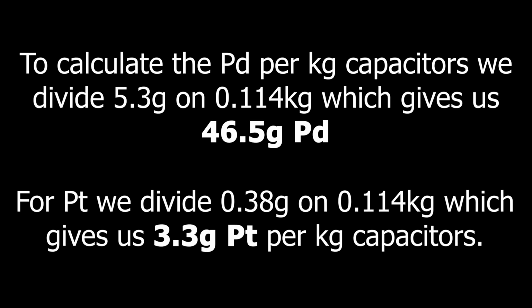To calculate the palladium per kilogram capacitors, we divide 5.3 grams by 0.114 kilograms, which gives us 46.5 grams palladium. For platinum, we divide 0.38 grams by 0.114 kilograms, which gives us 3.3 grams platinum per kilogram capacitors. To further purify the button, I put it in a Portland cement cupel.